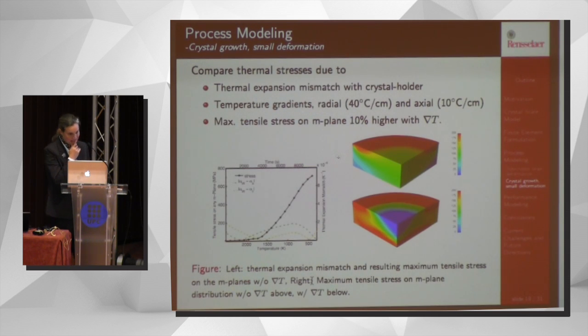So the thermal expansion mismatch between the aluminum nitride and the crystal holder, here is showing that as a function of temperature along the different directions, along the A and the C direction of the crystal. So this is the difference between the thermal expansion coefficient as a function of temperature. The green is along the A direction. The A direction is the transverse direction. The C direction is the axis that they're growing.